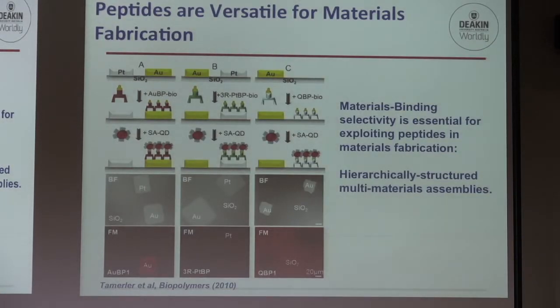Now, peptides, I just wanted to show you this to convince you that they really can be selective and they can be used in multi-materials fabrication. So in this case, they're using a gold binder peptide and a platinum binder peptide, and also one that will bind to silica. And you can see here from the images where they've conjugated a quantum dot that shows up as red in these images, that if they stick the quantum dot to their gold binder and expose it to this surface, you can only see the peptide stuck onto the gold part of the multi-material surface. So the background here is silica, you've got a platinum pad here and a gold pad here, and it's only sticking onto the gold pad.